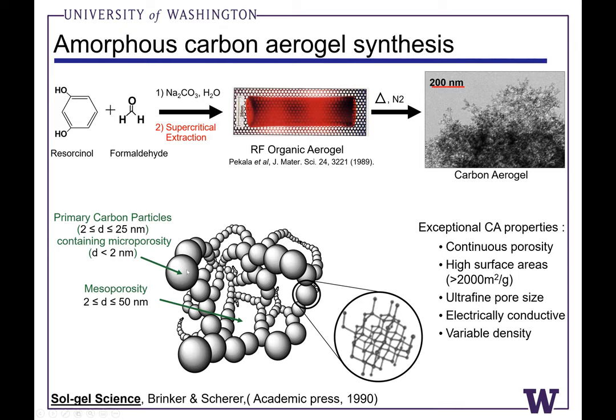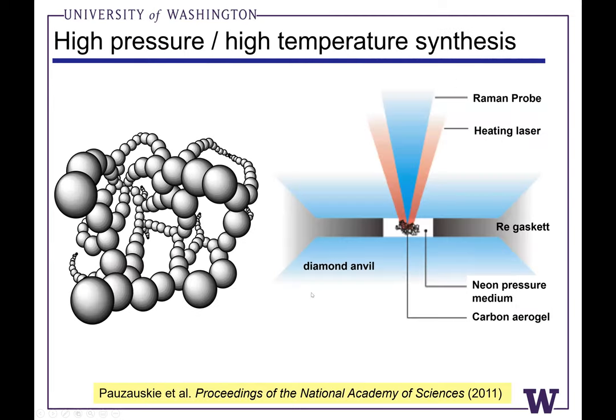And so these are really fascinating materials that have sort of mass fractal microstructure that you can think of sort of like a pearl necklace, like black pearls instead of white pearls. And these are connected in three-dimensional space. And the goal in our research is to dope this hydrocarbon material with molecular precursors that have well-defined heteroatoms. And then we can undergo a high pressure, high temperature phase transition from amorphous carbon to diamond in a laser heated diamond anvil cell. So that kind of gives a quick overview of the experiment.